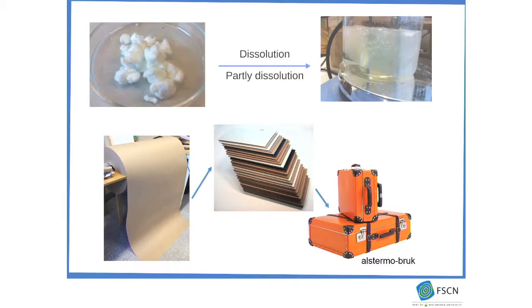cellulose dissolution. Because there are a lot of solvent systems nowadays that can efficiently dissolve cellulose or partly dissolve cellulose: the ionic liquid and also some other solvent combinations like sodium hydroxide and urea, lithium hydroxide and urea. And we chose sodium hydroxide and urea because it's a green chemical. It's not hazardous to the environment and it's relatively low cost. The process is also under mild conditions. We can control it.